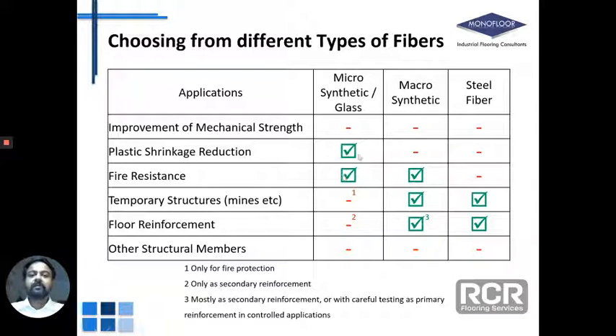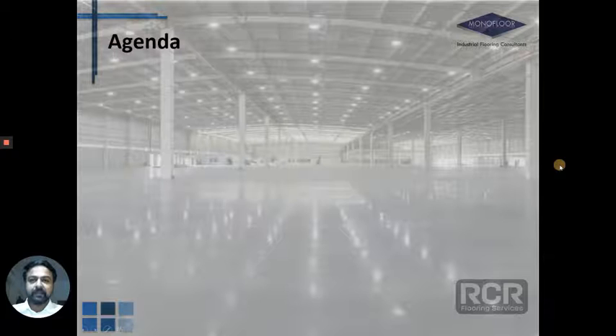Just to summarize different types of fibers and how they are relevant to different applications, it has to be noted that microsynthetic fiber is only a secondary reinforcement that's used for shrinkage cracks. That's also mostly in the plastic state. Macrosynthetic fiber can be used for similar applications. It can be used as a replacement to rebar with careful testing of the ductility contribution of these fibers. Steel fibers, of course, can replace conventional reinforcement in most of the flooring applications.